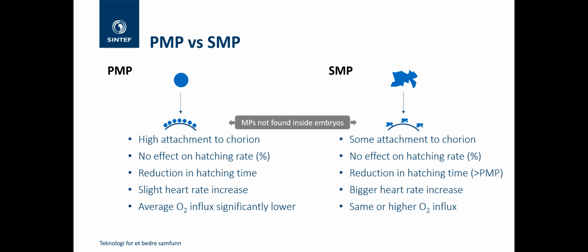When we looked at the same endpoints for the secondary, we saw that there was some attachment, but definitely less of the secondary particles. There was no effect on hatching rate. There was a much bigger reduction in hatching time, and a bigger heart rate increase. But there was the same or even a higher O2 influx into the chorion, into the embryo.